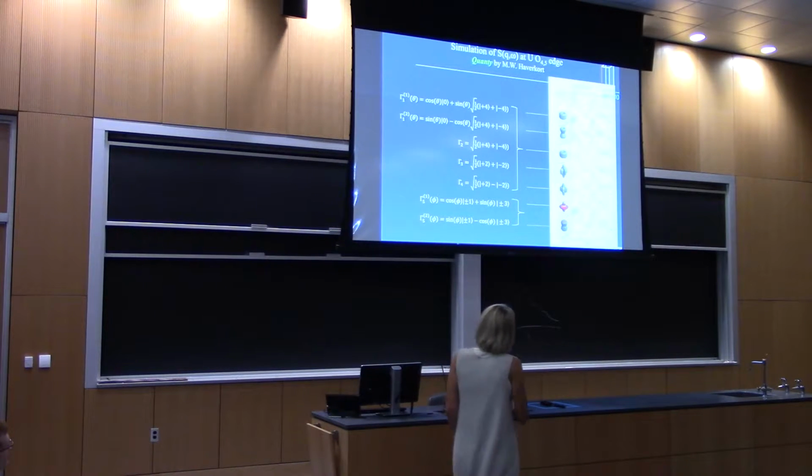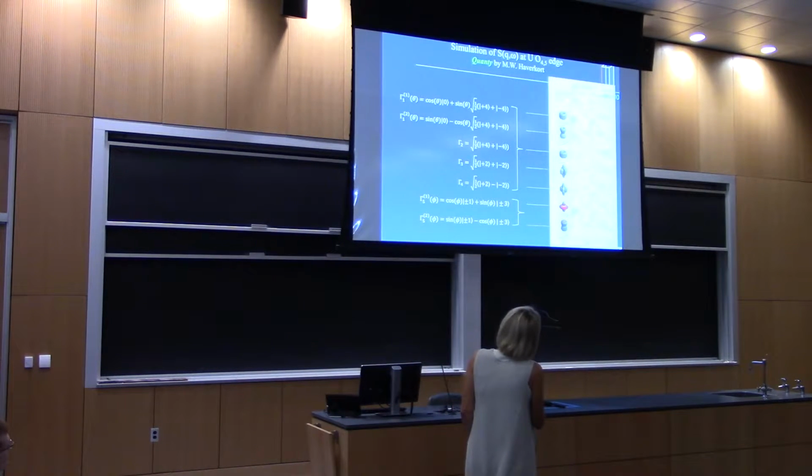We have now done the same simulation for all crystal field states here, gamma 1 to gamma 5. And we compare this now, so this here corresponds to these crystal field states. What I'm showing you here is always where you have the biggest contrast. So I have the gamma 1 theta 90 degrees. That means I have a pure JZ form.